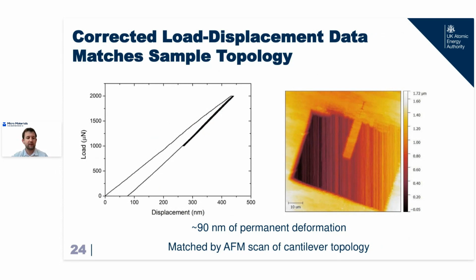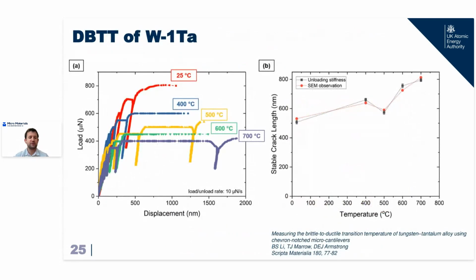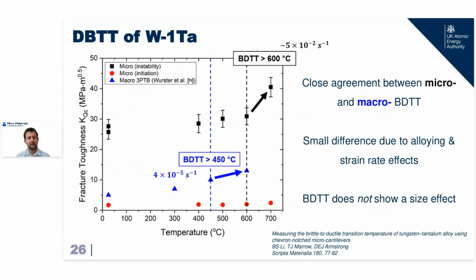So we can combine these two things, this clever chevron notch geometry as well as this very stable system, to start doing ductile brittle transition temperature studies. On several beams at several temperatures, we can extract our elastic plastic fracture toughness and our stable crack length. We can plot these out as a function of temperature and understand how our ductile brittle transition temperature changes as a function of material or eventually as a function of radiation damage.